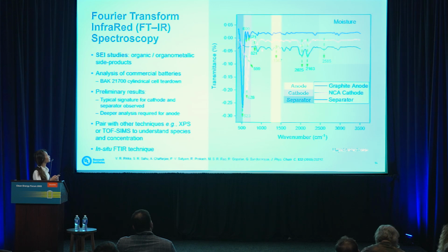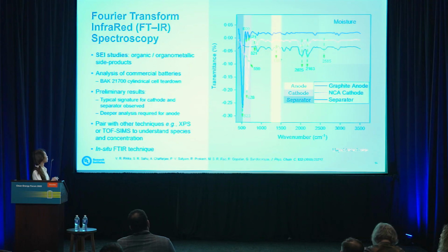On the anode side, we typically see a peak at about 1367, which is the sp2 graphite vibration mode. But we don't really see it here, so we need to analyze why we do not see it. Is the graphite somewhat not pure, or is there something going on at the surface? Some other techniques that we can pair with are XPS or TOF-SIMS to really understand the species and concentration.